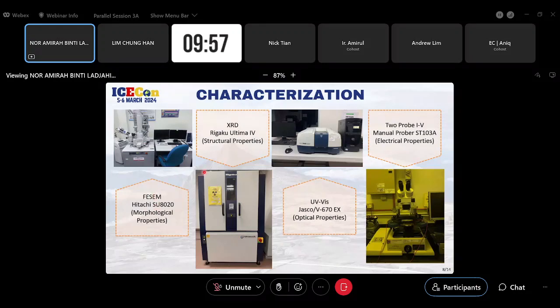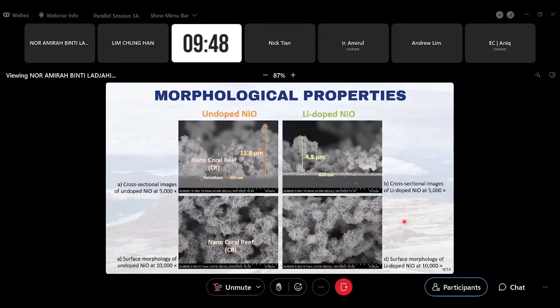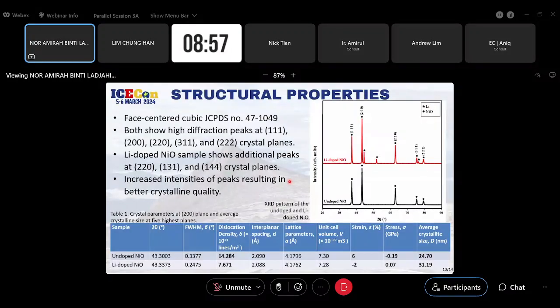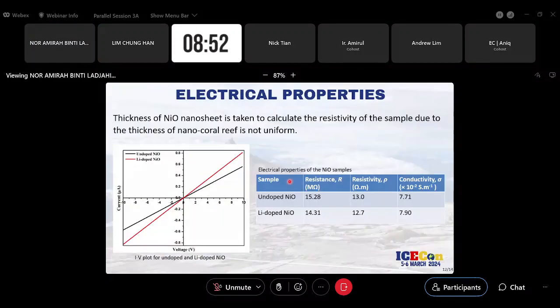First, we use FESEM, this one. We use XRD, UV-Vis, and also IV measurement. So moving to the result section, for morphological part from FESEM image, we can see here both undoped and lithium doped produce a nanosheet. Nanosheet is this thin layer. Then it's also produce a nanocoral reef, as you can see here, nanocoral. So from here we can see that the nanocoral is not uniform, so we cannot use this thickness to measure other properties. So we use nanosheet thickness to measure properties. For other result like structural, optical, and electrical, I will conclude in the conclusion part.